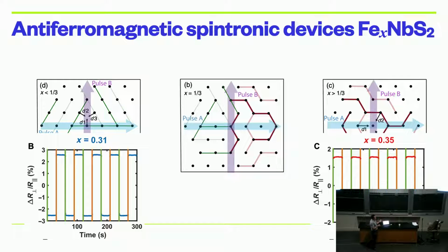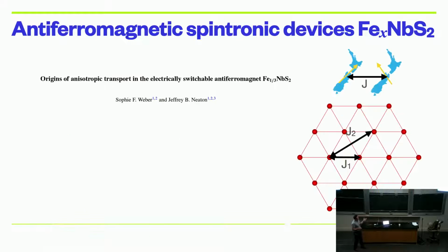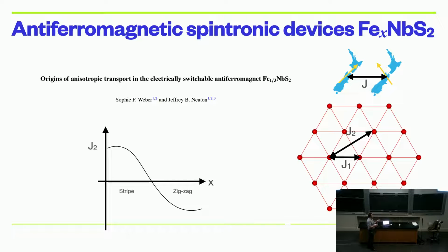And you might not be surprised to know that once you had something right on stoichiometry, this signal almost completely vanished. The two things completely canceled out. So why does this happen? Well, we worked with some DFT people. They calculated what all the exchange parameters are. And it turns out you have to go to your next nearest neighbor interactions, not just between your immediate neighbors on your triangular lattice. And once you do that, you can actually get zigzag on one side and stripy on the other.